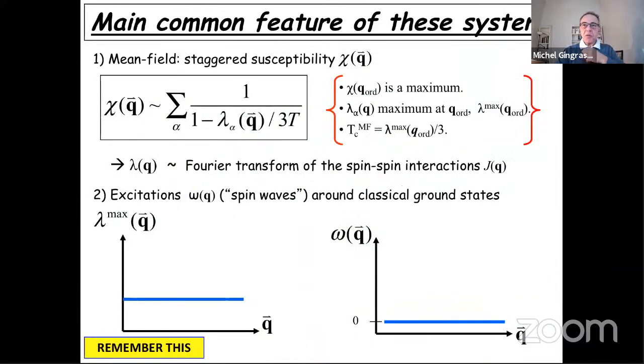Okay, so for the experts, where does that physics come from? One way to see that these lattices with triangular shared units or shared tetrahedra units are so prone to have this degeneracy is if you do a mean field calculation and you calculate the staggered susceptibility, you find that actually there are modes which are massless or go critical all at the same temperature over the whole Brillouin zone. So there's no selection of a single ordering wave vector at the mean field critical temperature. There's an extensive number of massless modes at the phase transition.